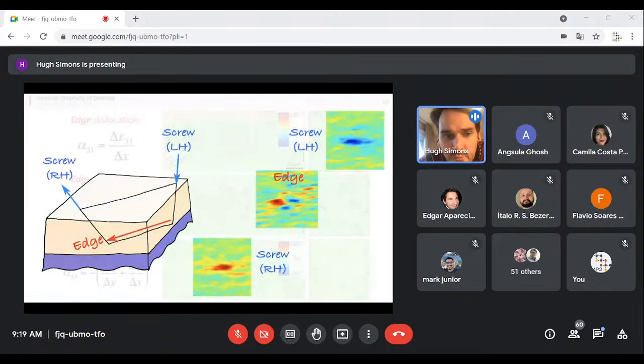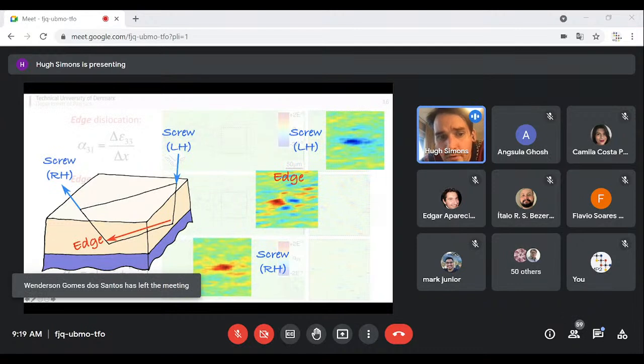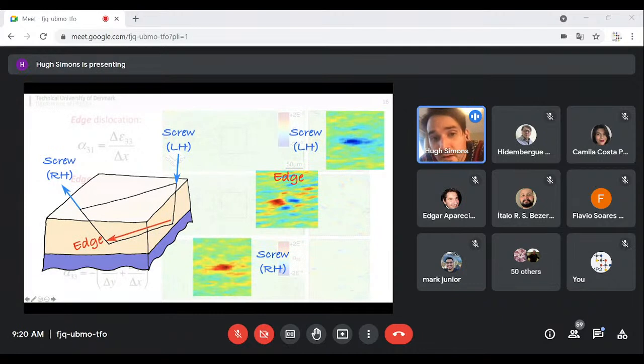And so this fits very beautifully, I think, with this image of misfit dislocations in thin films. So what we're actually seeing is the screw dislocation from the surface to the substrate film interface as one of these dots. And then we're seeing an edge dislocation propagating between the film and the interface, and then coming out of the sample again as a screw dislocation. And we can show this, I think, quite clearly now.